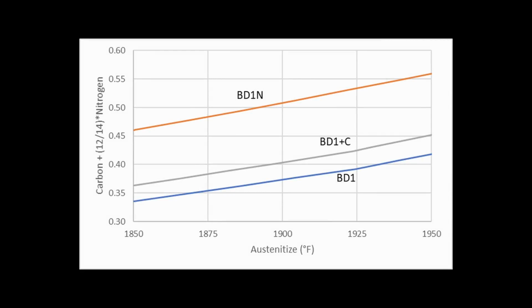So then we have the question of why not just add more carbon instead of nitrogen. If you wanted more hardness, just like from the nitrogen, just add more carbon. So I did some fancy calculations in Thermo-Calc, which is a modeling software pretty common in the metallurgy industry. I added the same amount of carbon as you would have from the nitrogen and plotted out how much carbon in solution there would be. Adding that much carbon only barely bumps up your carbon in solution. When you plot it out, it almost looks like it didn't change at all, especially compared with the BD1N.